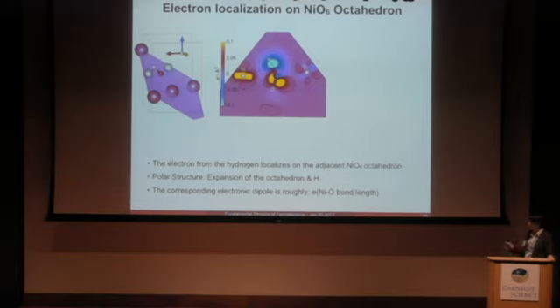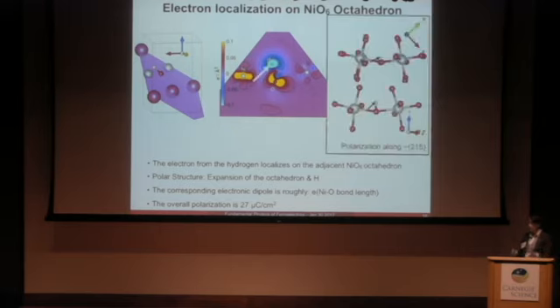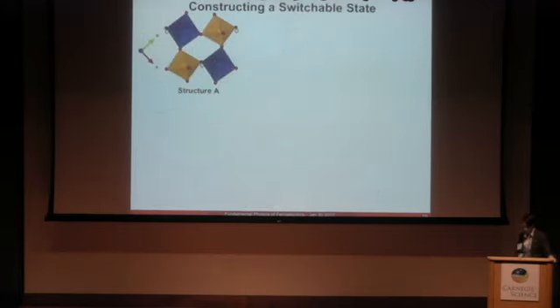And because of the electron localization on this, we have this charge-ordered structure now. So we have a purely electronic dipole as well that is roughly an electron times the bond length, the nickel-oxygen bond length. So we end up with an overall polarization of about 27 microcoulombs per centimeter squared. And it is not in a trivial direction. So I'm trying to orient you in the direction of the polarization. So it's going from the center of the octahedra towards the hydrogen. So we have this relatively large component along the c-axis, and then otherwise it kind of remains along the 1-1-0 direction. So how do we construct a switchable state?